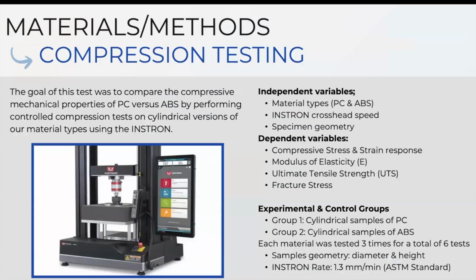So we decided to go with compression testing rather than tensile or three-point bend because we determined that most of the force in the finger joint when bending or when having other forces act upon it will be compressive forces. And so the goal of our testing was to compare the compressive mechanical properties of our materials, so our PC and our ABS, by performing controlled compression tests on cylindrical versions of these materials using an Instron machine.